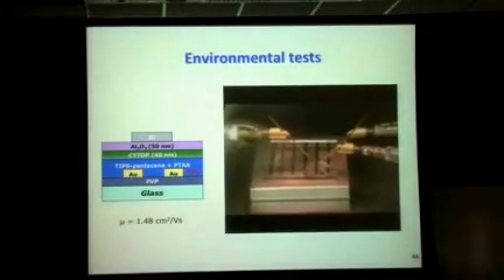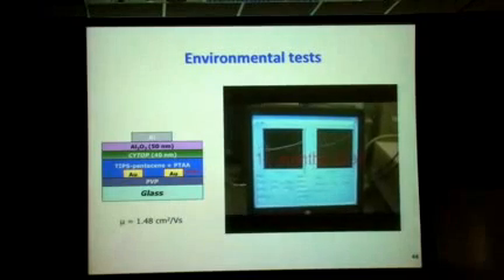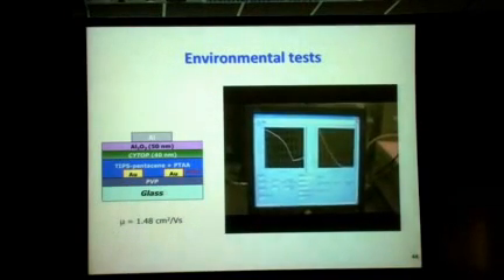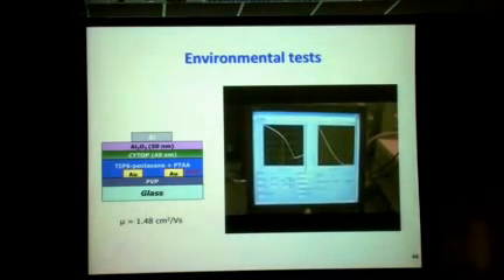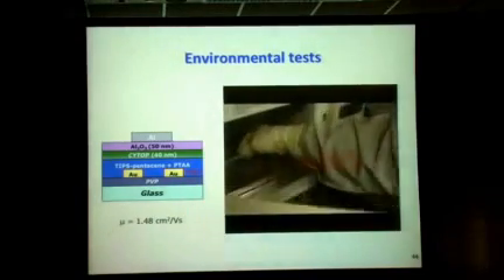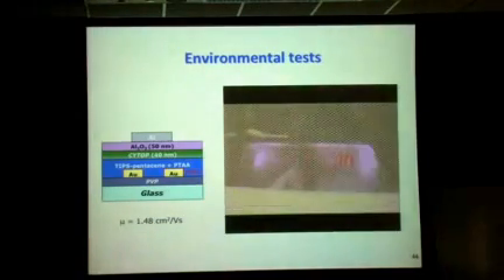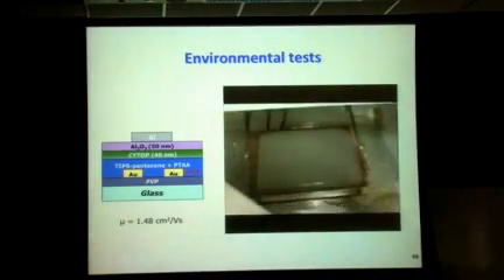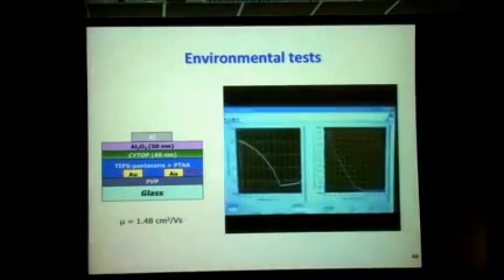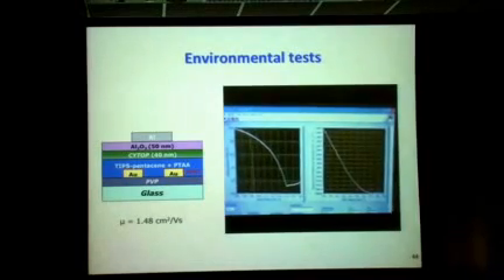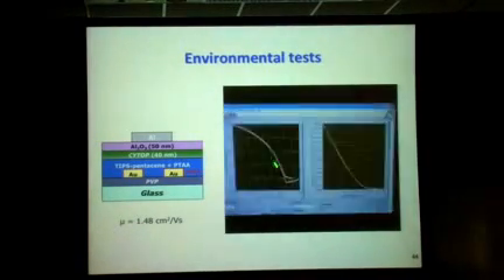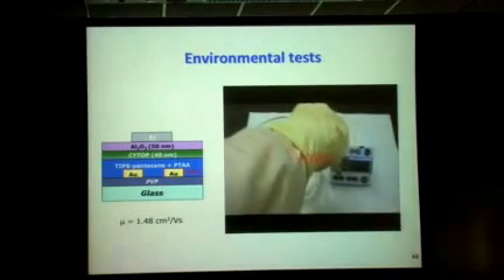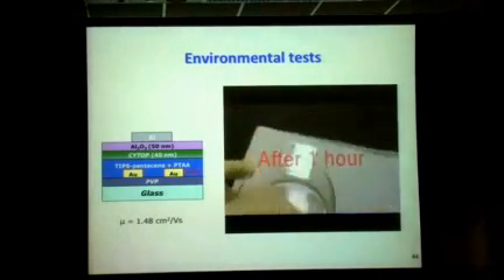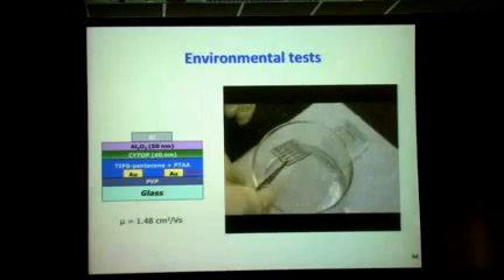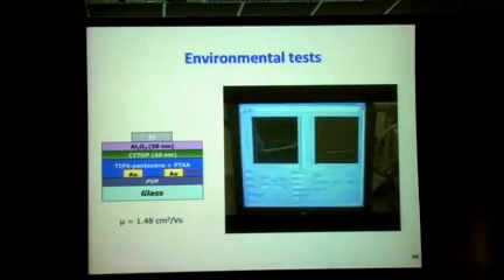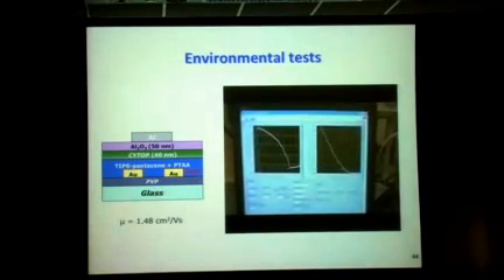To illustrate the stability, I have a movie that shows leaving these transistors on the shelf for about 11 months, then putting them back in the system, and they're still working. But the postdoc doing the measurements was tired of seeing no changes, so he put them in a plasma chamber for 5 minutes wanting to really destroy them. They were still working. Next he immersed them in water for an hour, dried them a little with nitrogen, put them back into the semiconductor analyzer, and the transistor is still working.